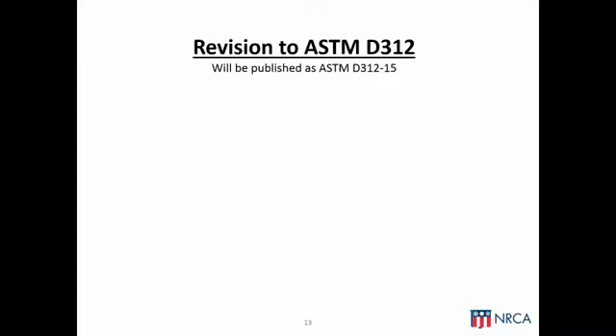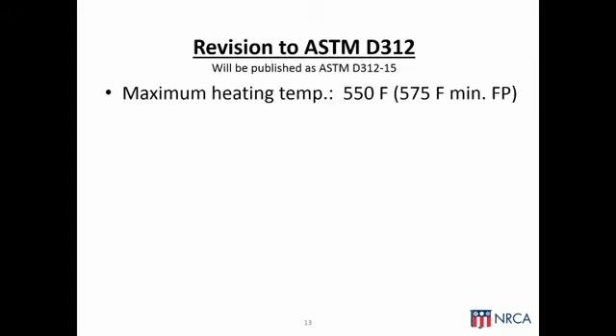Just last Wednesday, a new revision to the ASTM standard for asphalt, ASTM D312, was approved at an ASTM meeting in New Orleans. And that revised standard will be published probably within the next several weeks, and it will be given the designation ASTM D312-15, and the -15 indicates the year or edition date. One of the key points in this new revision of the ASTM D312 standard is a requirement that the maximum field heating temperature for asphalt, whether it be a kettle or a tanker, be 550 degrees Fahrenheit.